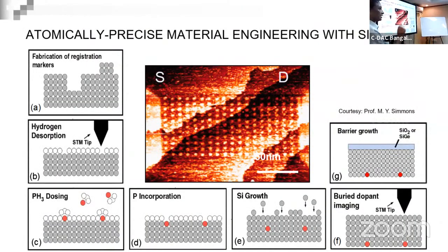So they create these silicon doped qubits using single phosphorus atoms in a very interesting manner. They take silicon, and then they use an STM to selectively create holes in silicon. Because it's an STM, you can actually go and pluck atoms out one by one, because the stability of the STM allows you to access individual atoms. So you pluck one atom out, and then you put phosphine gas over there, and the phosphorus comes, and these red circles are phosphorus. They get embedded inside silicon, and then you grow silicon again. So you now have individual phosphorus atoms precisely where you want them, like that picture out there. You can form arrays of single phosphorus atoms, dopants, creating a unique structure.